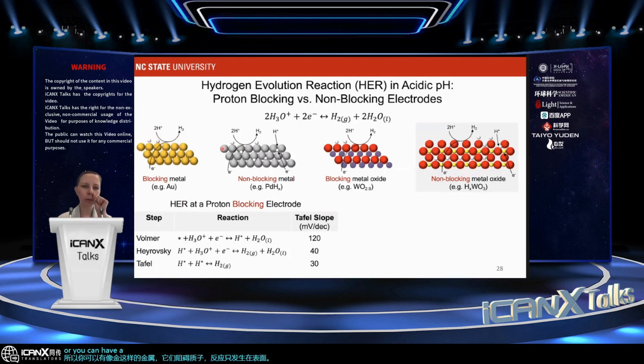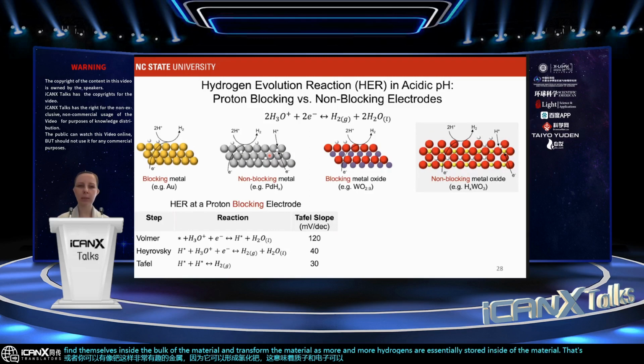Or you can have a metal like palladium, which is very interesting because it can form a palladium hydride. That means that the protons and electrons can find themselves inside the bulk of the material and transform the material as more and more hydrogens are essentially stored inside of the material. That's why palladium has been considered as a hydrogen storage material.